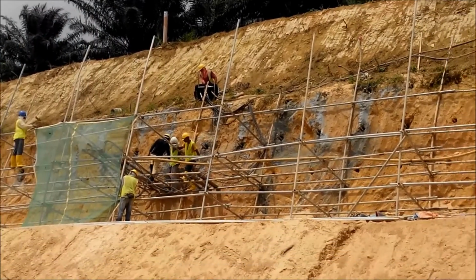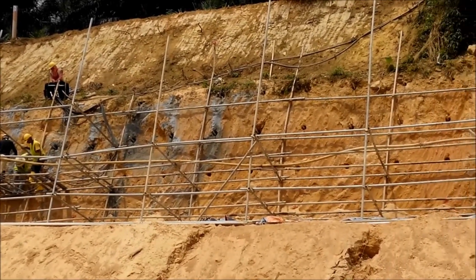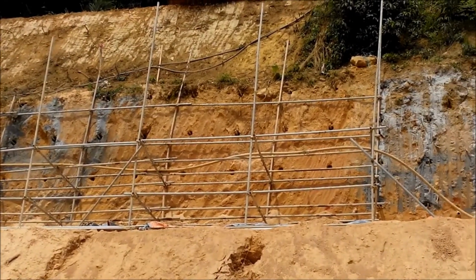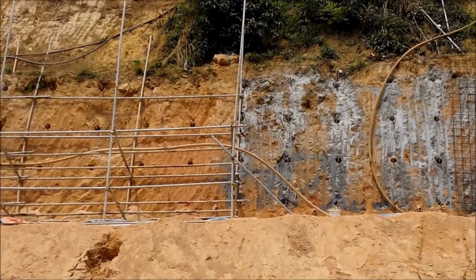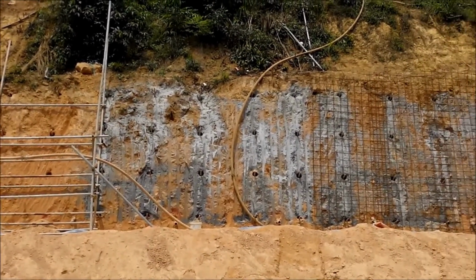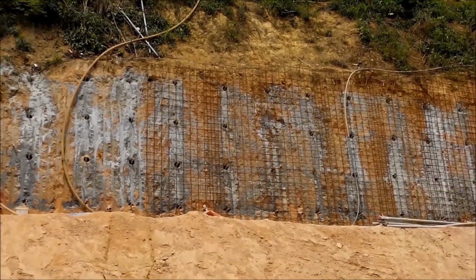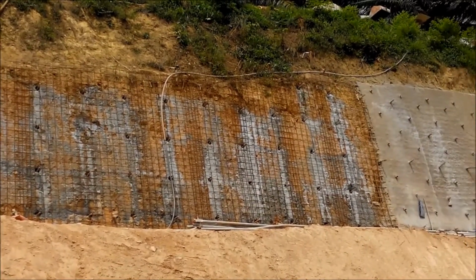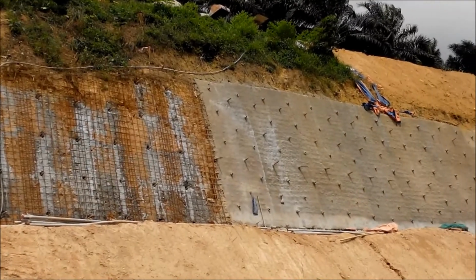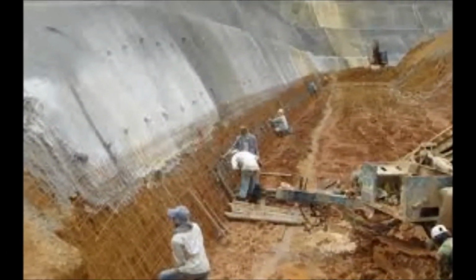Cracks sometimes form on this protecting surface due to poor water pressure build-up, which requires immediate repair. As the gunite cures, it will shrink and there will be the development of transverse cracks. Shrinkage cracks allow water to seep into the subsoil, which can result in localized soil erosion problems. When shrinkage cracks develop, the wire mesh may also break apart. Guniting is very vulnerable to soil movement.